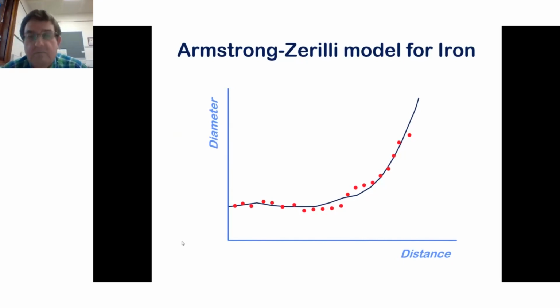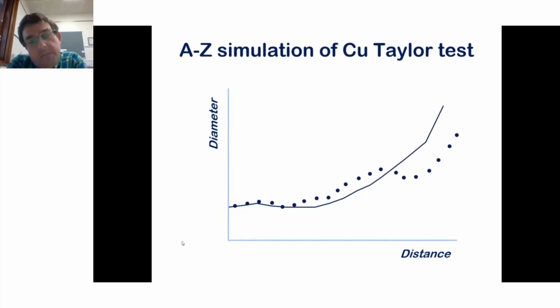Okay, let's not do iron, let's do copper. Copper, okay. So the diameter of the rod has this bulge in it about two-thirds of the way along. The diameter is quite big, and then that bulge shrinks. And the model says it should just expand in a monotonic fashion. Actually, something else is happening. Here, we're getting onto what's going to be a theme that I will be bringing up again and again through the rest of these presentations.